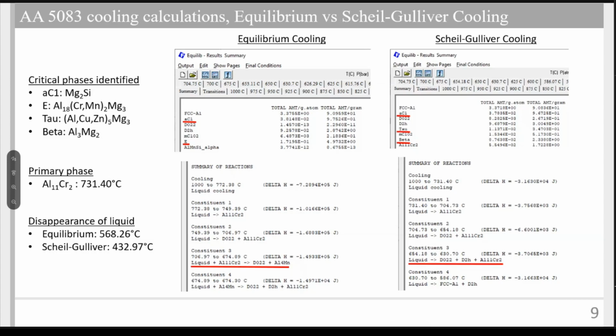Looking at the invariant reactions happening during cooling, we can see that the primary phase formed in this case is Al11Cr2, and the Al matrix only occurs later on. An important thing we can see is that the final disappearance of the liquid happens at two different temperatures depending on which mode you're using for the cooling. Here in equilibrium cooling, it happens at approximately 570 degrees Celsius, and for the non-equilibrium cooling, it happens around 430 degrees Celsius.